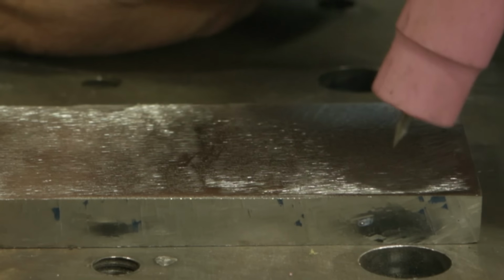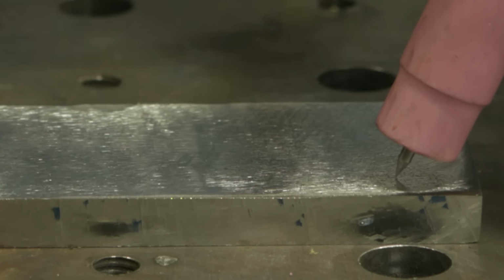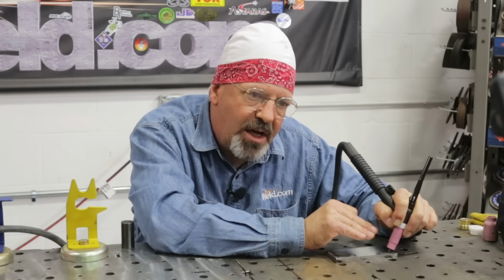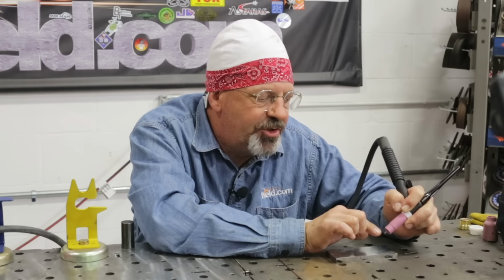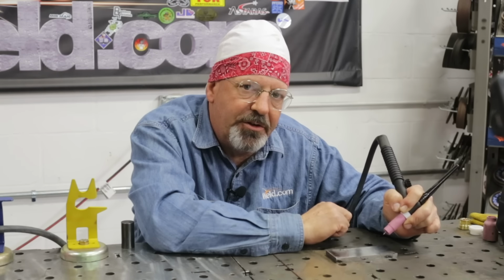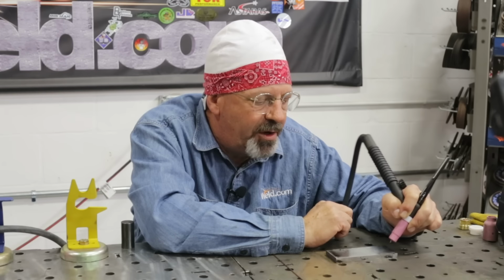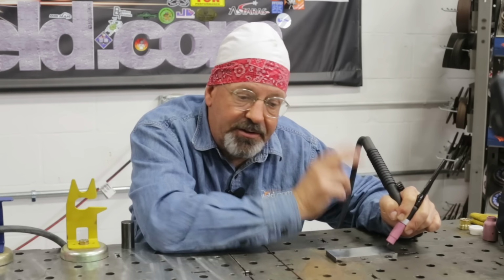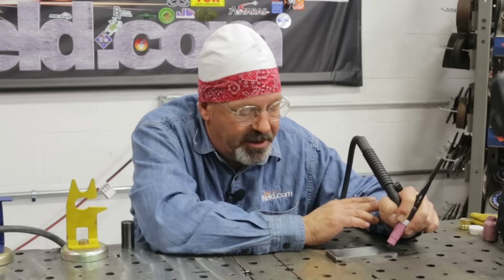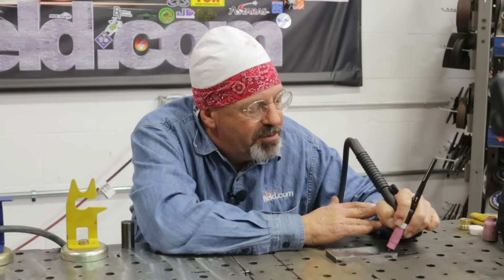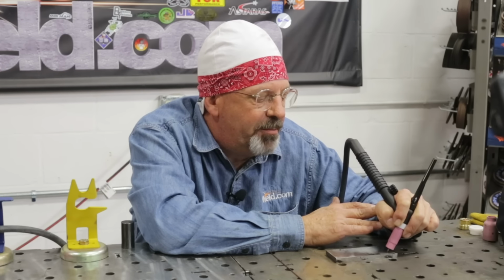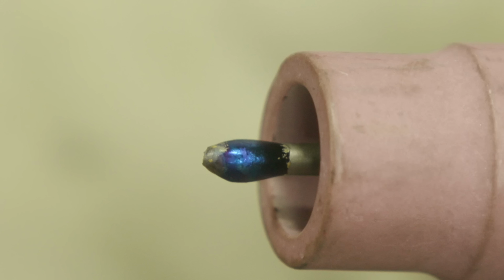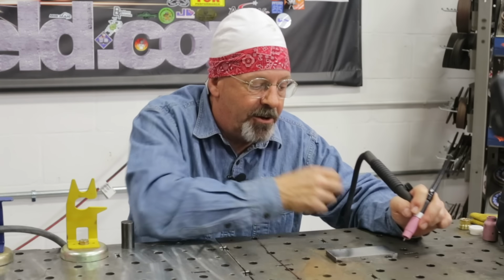Obviously, if you touch the tungsten into your weld pool, you're done. You need to stop, and you need to resharpen and clean this point on your tungsten. That's very important. I still dip a tungsten. I do it all the time. It happens. But I've seen a lot of people dip and dab, and they'll get this tungsten all manked up on the end. It looks like a Q-tip, and they're trying to weld with it. Not good. We're going to reproduce all these problems that can go on.